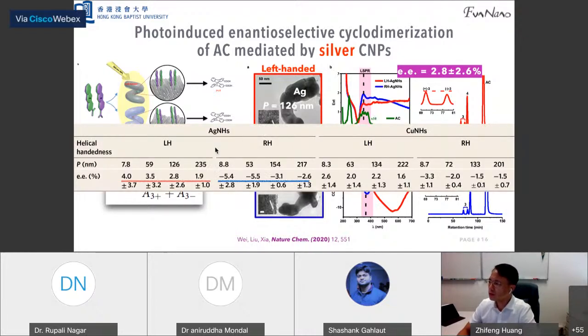So we change the pitch of the silver nanohelical structures from 8 nanometer all the way to more than 200 nanometer. And the common result is for the left-handed silver nanohelical structures, the EE value is positive. That means we preferentially generate the +3 molecule. And on the right-handed, the EE value is negative. And we have generality. So the copper can also function as the photocatalyst, right? The left-handed, the EE values are all positive, and the right-handed, the EE values are all negative.